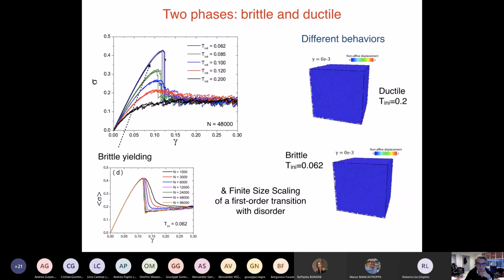And here, the different curves correspond to different values. T init is the temperature at which the system has been annealed before doing the quench at 0 temperature. So in this case, you see it's an extremely small temperature. So this is a super well annealed system. And the black line here is not a very well annealed system.